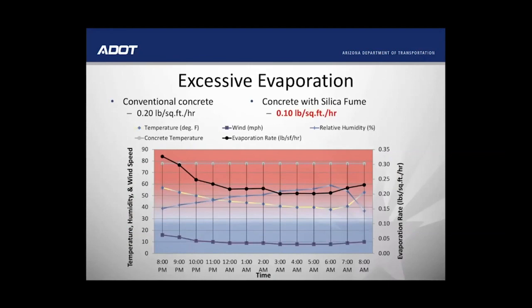Here we have a reasonably moist and cool condition, but with a wind speed of 8 miles per hour or more, that's the purple line down here with the squares, we have conditions not conducive to silica fume concrete. The evaporation rate, which is the black line with the dots, is well above 0.20 pounds per square foot per hour, even during the overnight hours. Placement of silica fume is very much dependent on cooperation of Mother Nature.